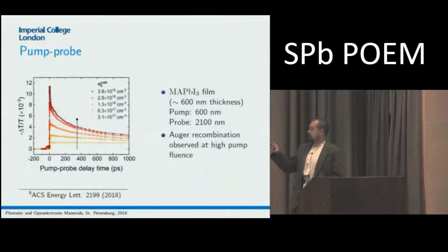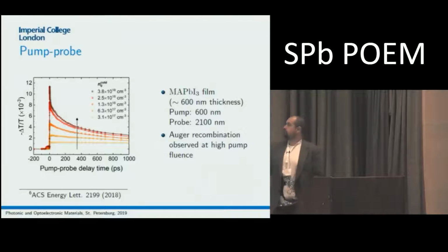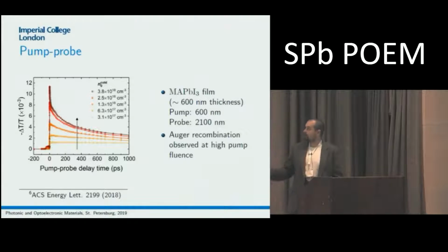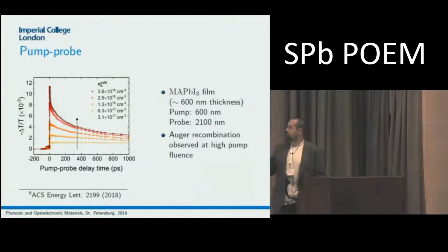These are some typical curves, pump intensity dependent pump probe measurements, and we can see that at higher intensities, at higher pump fluences, we can see Auger processes that result in faster recombination times due to energy exchange between the carriers.